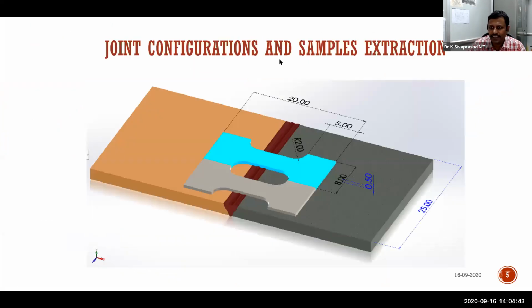Joint configuration at this stage, I just want to explain to you that this is assumed to be a dissimilar joint, A side and B side, and the joint is at the center. All the samples were extracted in the transverse direction. I told you that our width used to be two fingers' size, and when you are making a joint like this, your total width in this direction used to be less. We used to get some 40 to 45 maximum width after joint. So we have gone for a miniature tensile specimen.